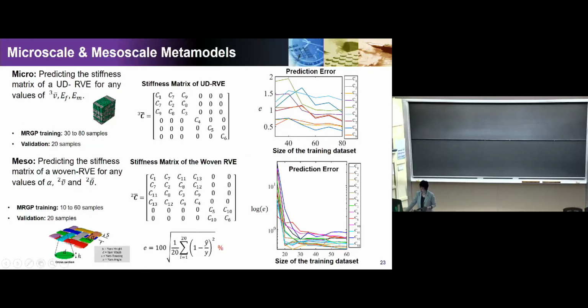Here are some details about the microscale level. We have a surrogate model to represent the constitutive relationship. For that stiffness matrix, the number of elements is slightly less than for the mesoscale, which has more elements. And this curve shows the impact of the training sample size on the error of different models. You can see that for this kind of training at the microscale level, 80 samples is quite sufficient.